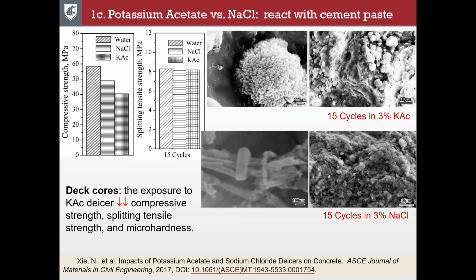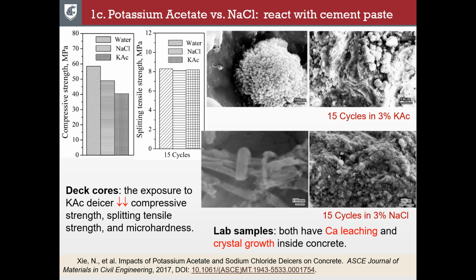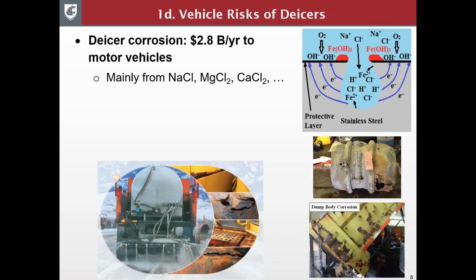More recently, we had some research demonstrating that, even in the case of sodium chloride, it's not just a physical interaction with the concrete. Actually, there's some calcium leaching and the formation of new crystals. In the case of potassium acetate, that's even more significant and caused significant reduction in compressive strength, split tensile strength, and microhardness. So in these cases, we demonstrate this calcium leaching out of the concrete and crystal formation inside the concrete, causing stress buildup inside concrete and eventually more severe cracking.